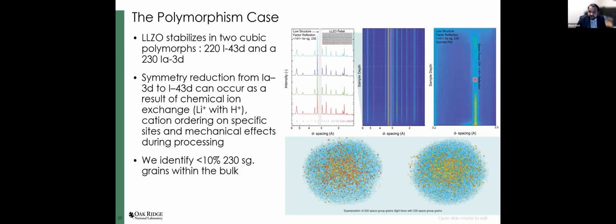And you can see that this distinct reflection that we have, the 141 in the 230 space group, is spatially not consistent across the thickness of the pellet, which is consistent with what we observed in HEDM, where you can see that while the blue dots are the 230 space group grains in the bulk, the location of the 220 space group grains is fairly stochastic.